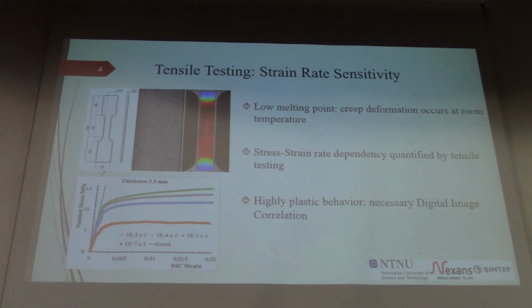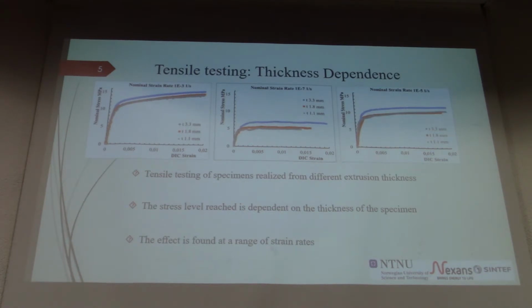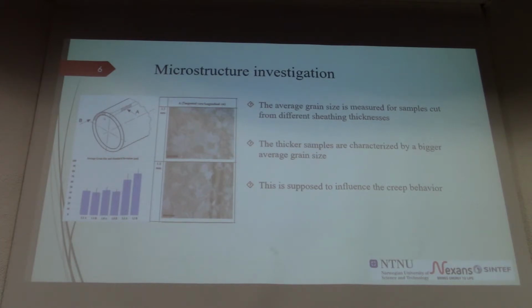at recrystallization temperature, basically. There is also an influence of the thickness, because we did this testing for different extruded thicknesses of the sheeting layer, from 1.1 to 1.8 to 3.3 millimeters, and the thicker specimen always reaches a higher stress level for a given strain rate. There's 10^-3, 10^-5, 10^-7. The idea is that this is influenced by the microstructure, and indeed the thicker specimens at 3.3 are found to have an average grain diameter which is bigger than what is found in the 1.1 and the 1.8 millimeter extrusions. So this would basically make the creep deformation harder.